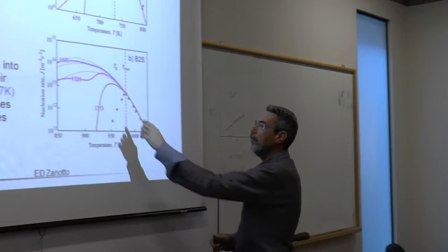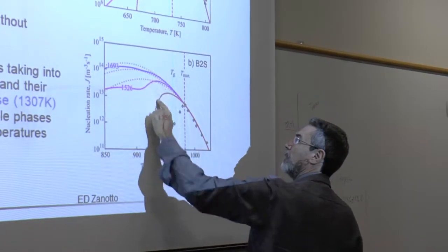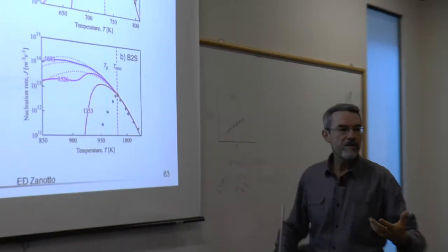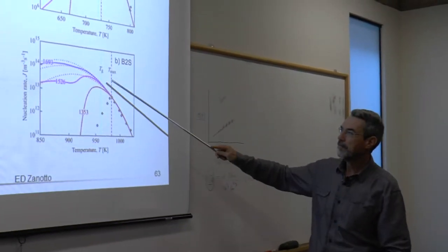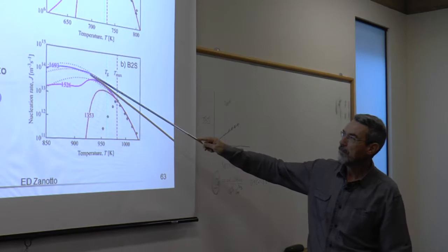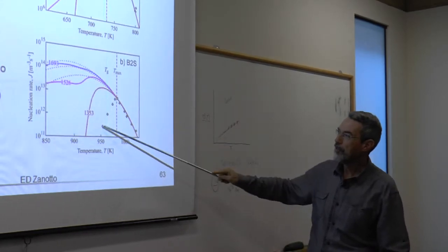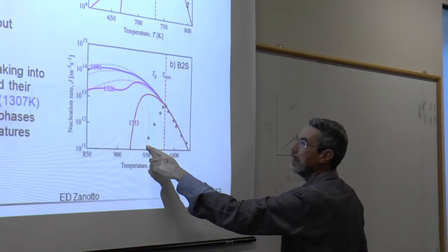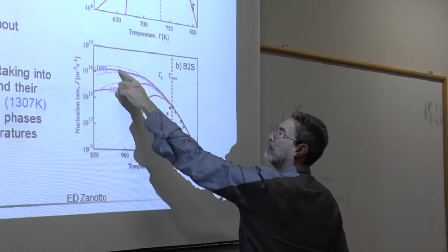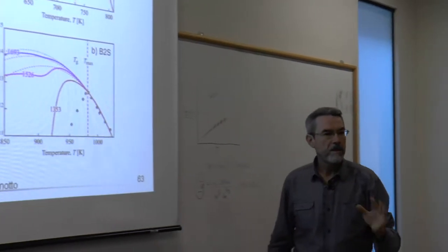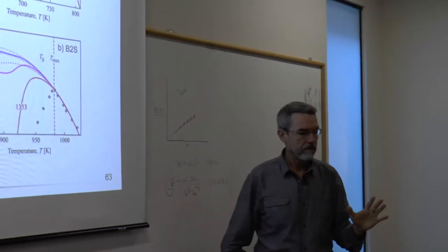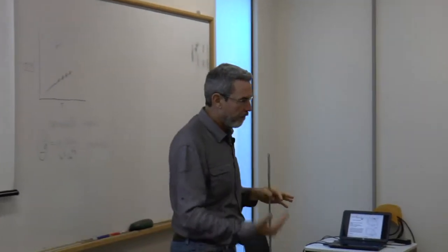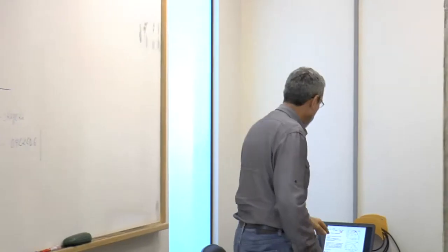It does make a difference here, because then they cannot relax so fast. But it does not explain the experimental data. Experimental data are here. The calculated values are here. Conclusion: stresses do not explain the failure of the classical nucleation theory.